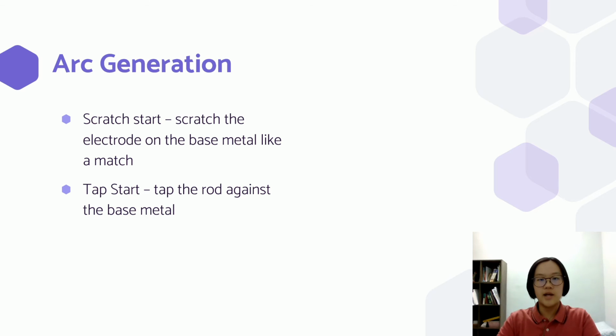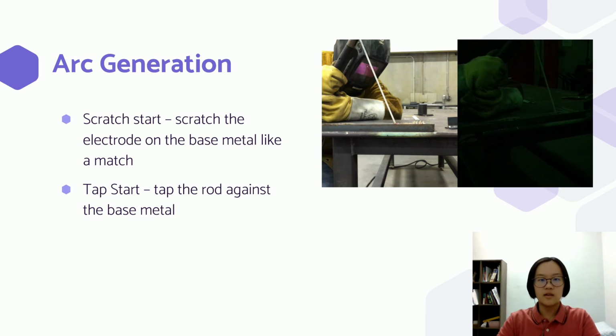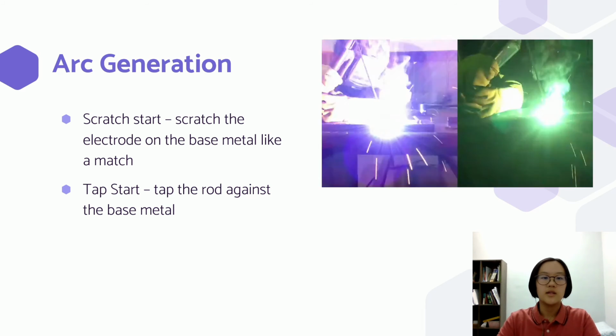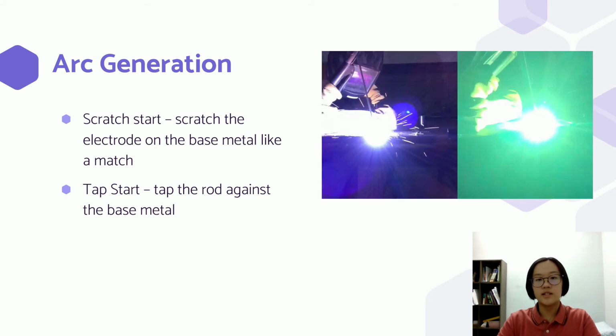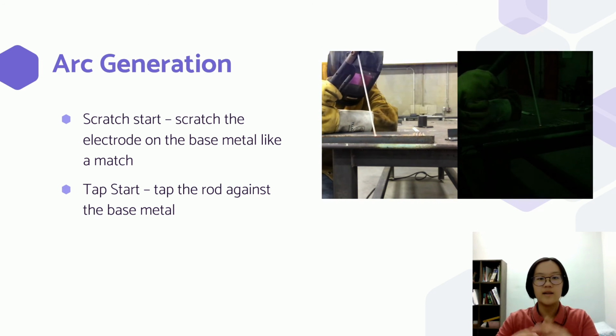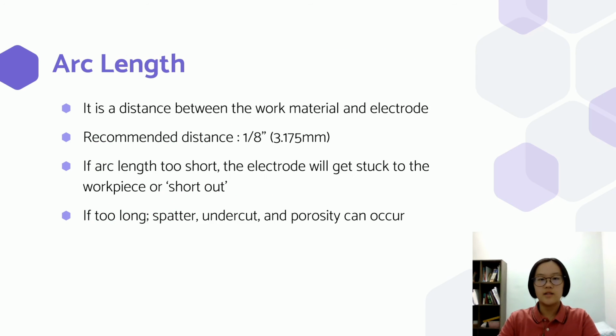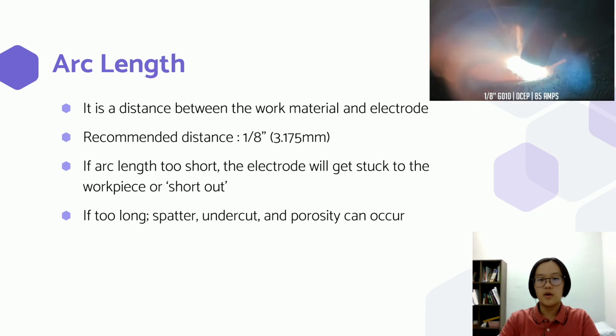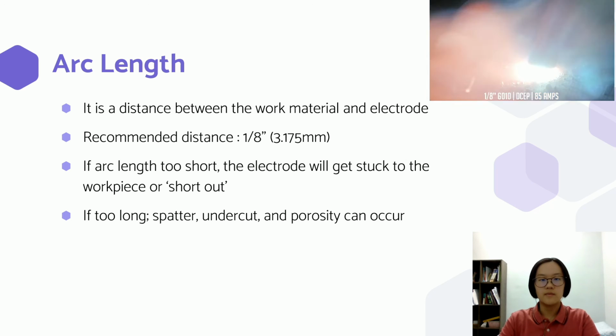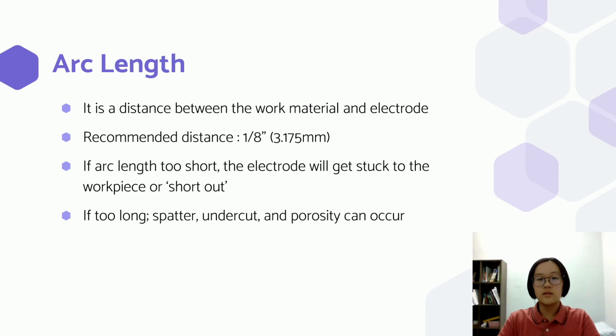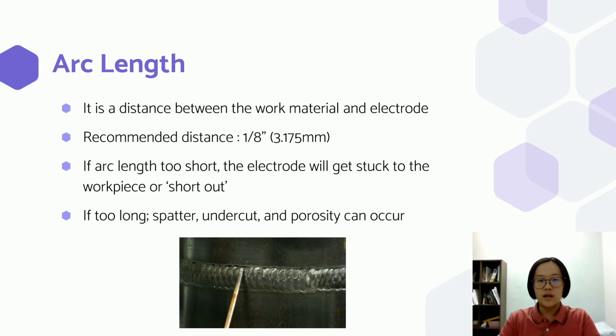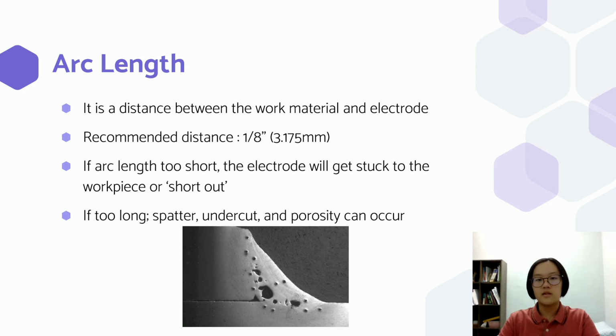There are 2 ways to generate an arc. First, scratch start, where you just scratch the electrode on the base metal like a match. Second, tap start, where you just tap the rod against the base metal. Arc length is a distance between the work material and electrode. The recommended distance is 3.175 mm. If the arc length is too short, the electrode will get stuck to the workpiece or short out. If it's too long, spatter, undercut, porosity can occur.